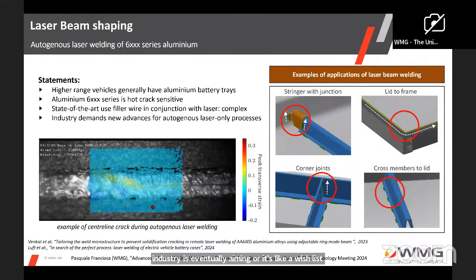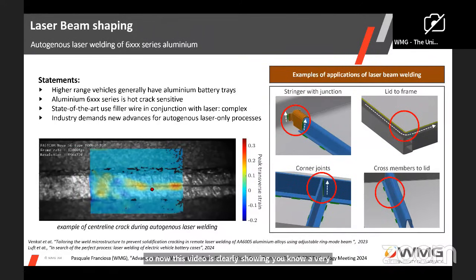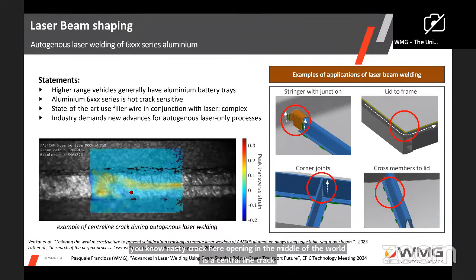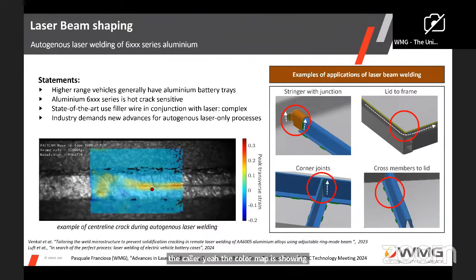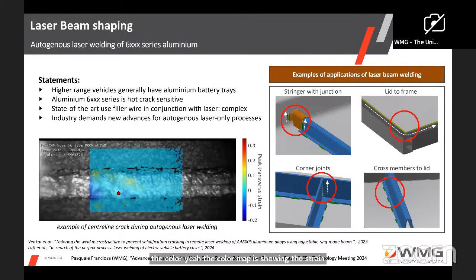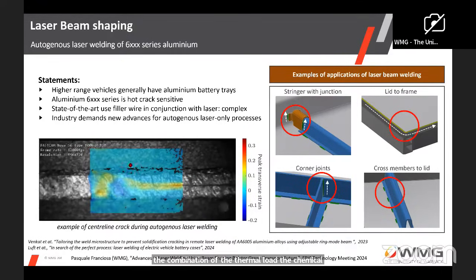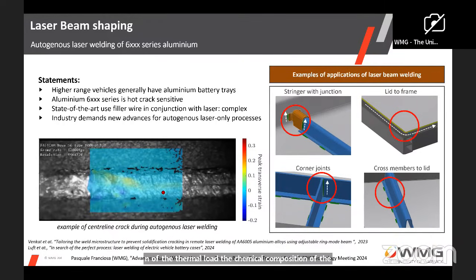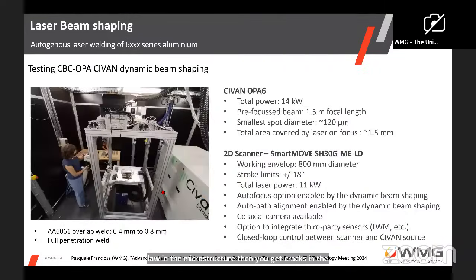So now this video is clearly showing a very nasty crack opening in the middle of the weld. It is a central line crack. The color map is showing the strain induced by the thermal load, and obviously because of the combination of the thermal load, the chemical composition of the alloy and the microstructure, then you get cracks in the end. So it means those welds are not really functional. So how we want to approach it is using beam shaping, dynamic beam shaping in particular.